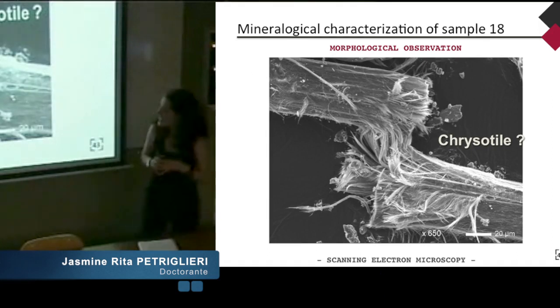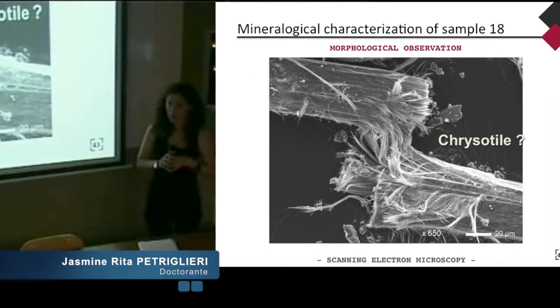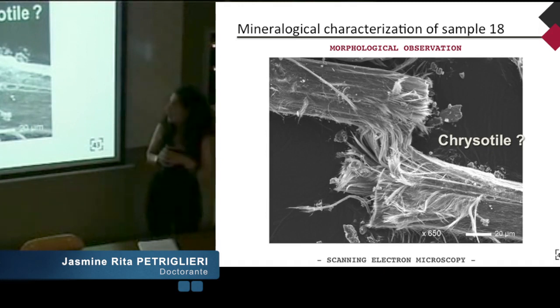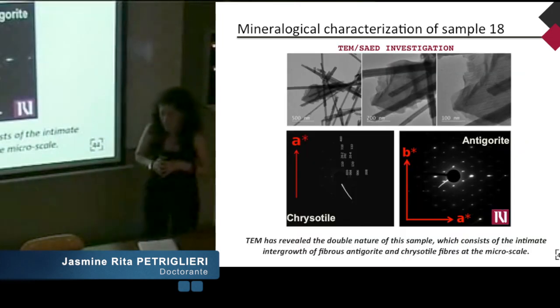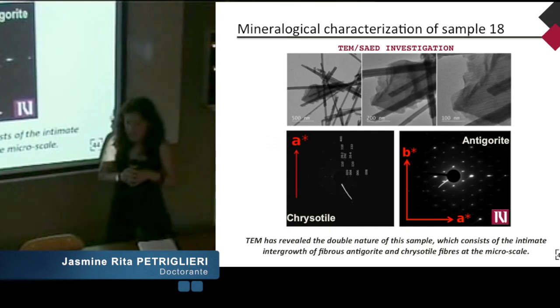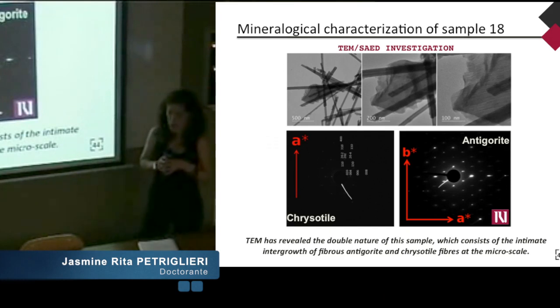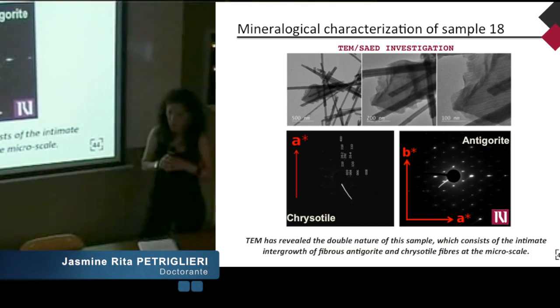To investigate the morphology, SEM images reveal a more fibrous aspect and the appearance of flexible fibers — is this chrysotile? Finally, TEM associated with diffraction patterns reveals the double nature of this sample, which consists of the intimate intergrowth of fibrous antigorite and chrysotile fibers at the micro-scale.